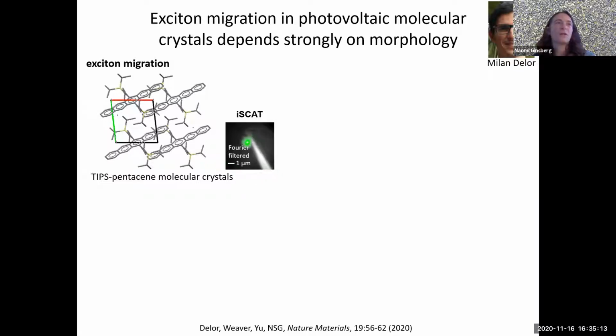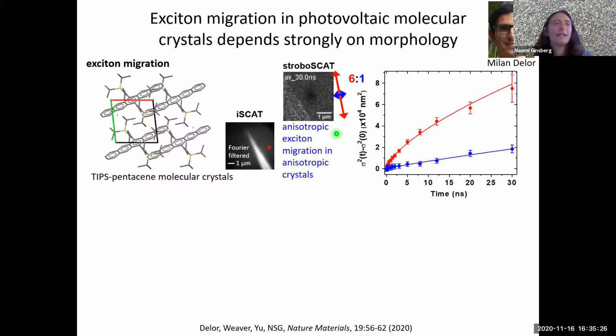You can see here there's, in the ground state image, a wedge-shaped domain, and it's flanked by these two other domains. And then if we pump in that red spot, in the bulk of one of the domains, we can measure a movie that looks kind of like that. And because the molecules are anisotropic and the crystal structure is too, the transport is not surprisingly anisotropic. It has a fast and a slow axis.